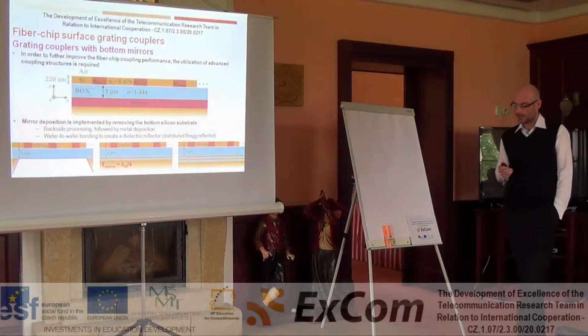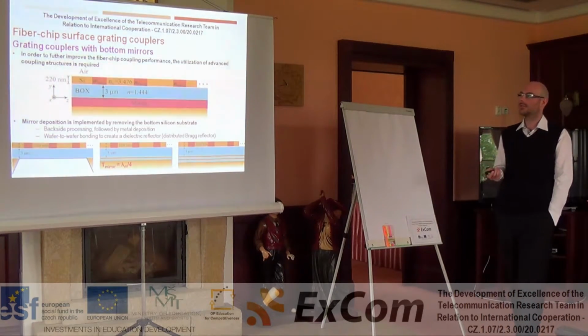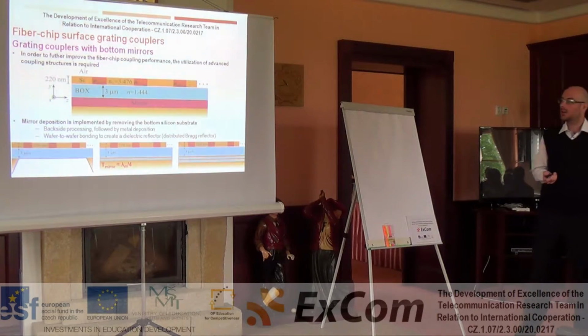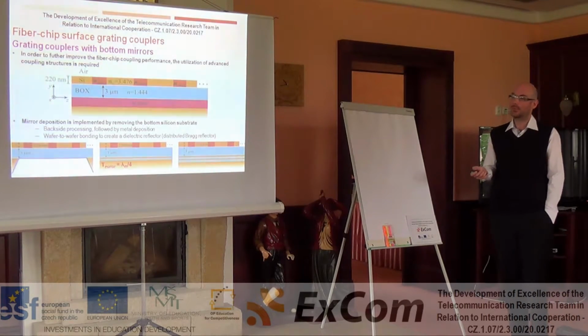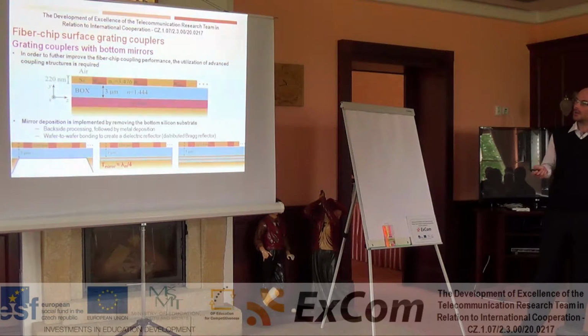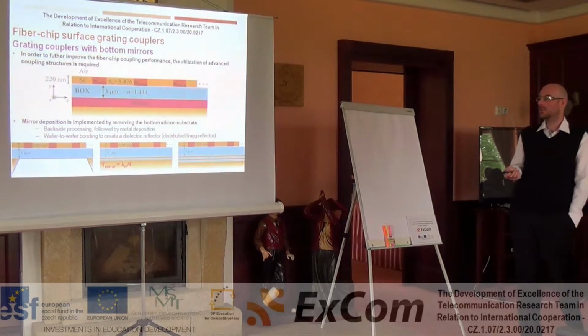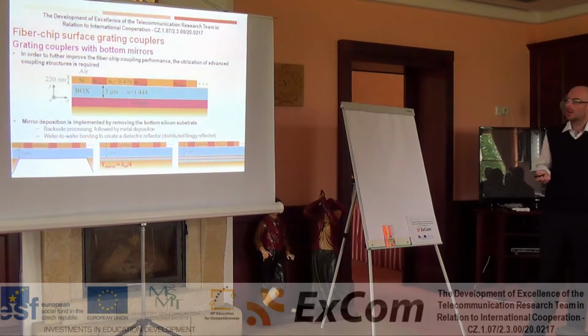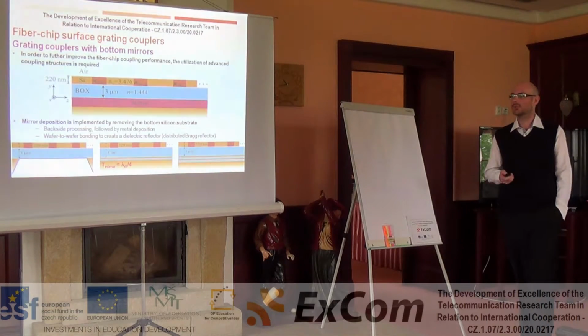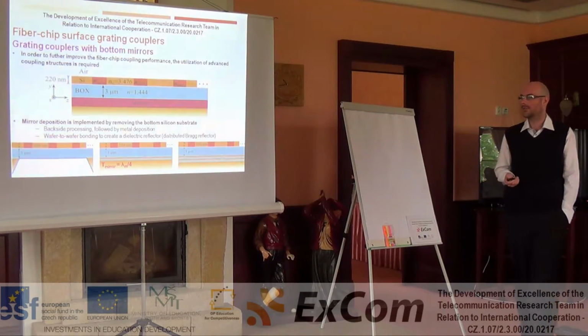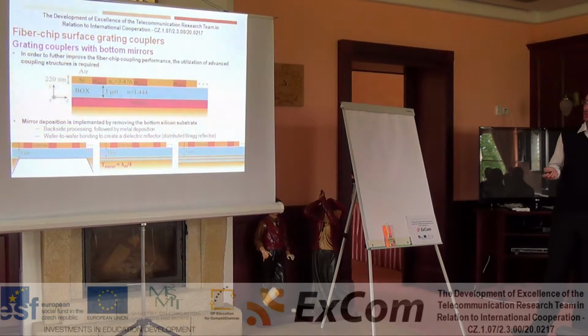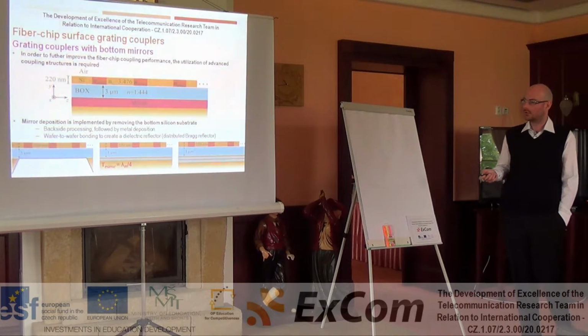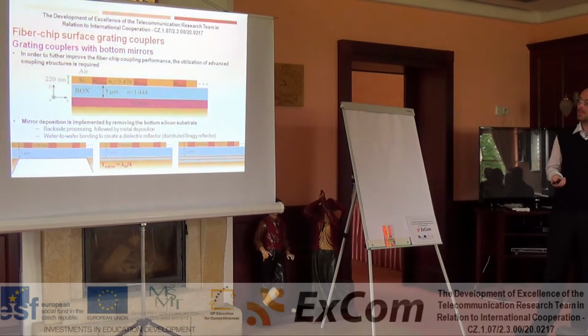Okay, the next way how we can increase the fiber chip coupling efficiency is by implementing the mirror structure in the bottom of the grating. Mirror deposition is typically implemented by removing the bottom silicon substrate by using backside processing followed by metal deposition, or we can use wafer-to-wafer bonding to create a dielectric reflector, as you can see on these two figures.